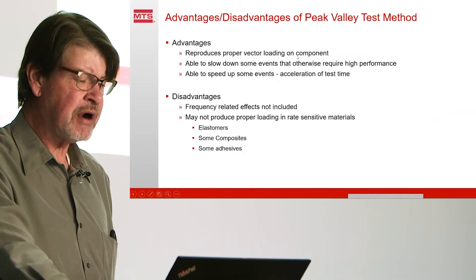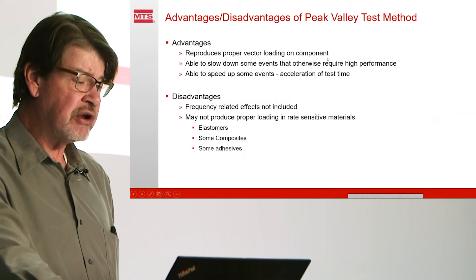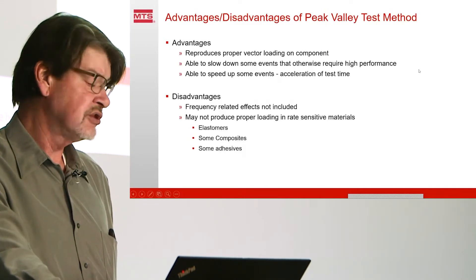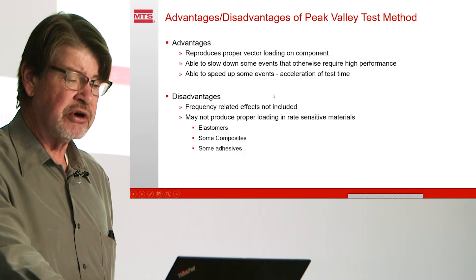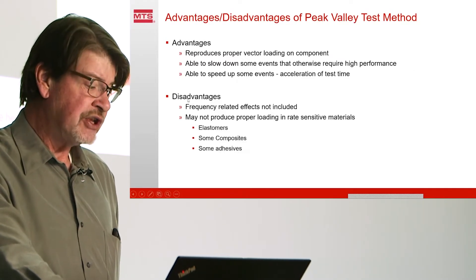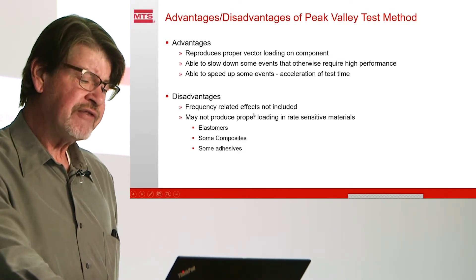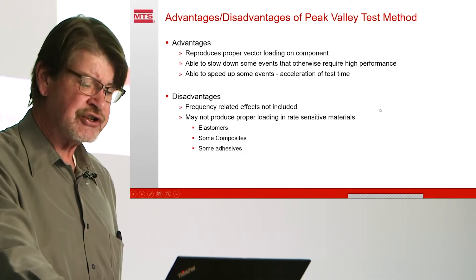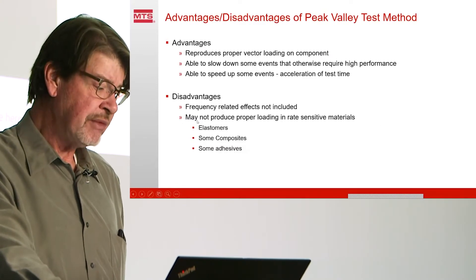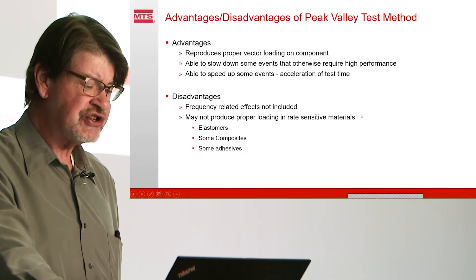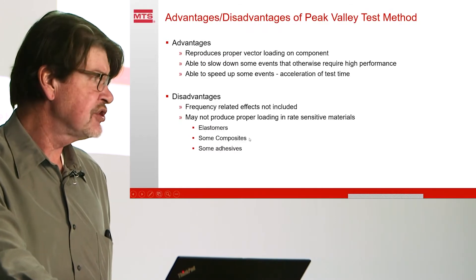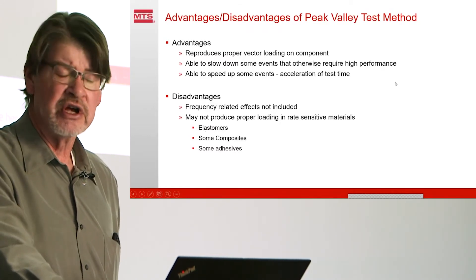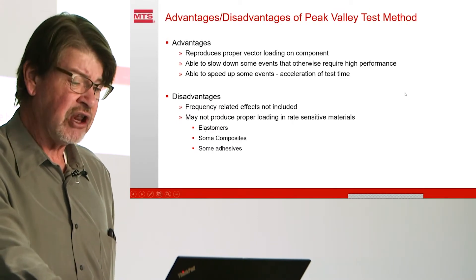The advantages are that we produce proper vector loading on the components, we can slow down some events that would otherwise require high performance, and we can speed up slower events to accelerate our test time. The disadvantages are that frequency-related effects are not included — if you're looking for free response characteristics, you're really not going to get it; this is all forced response. It may also not reproduce proper loading on rate-sensitive materials such as elastomers or adhesive joints, though those are not so common in truck components.